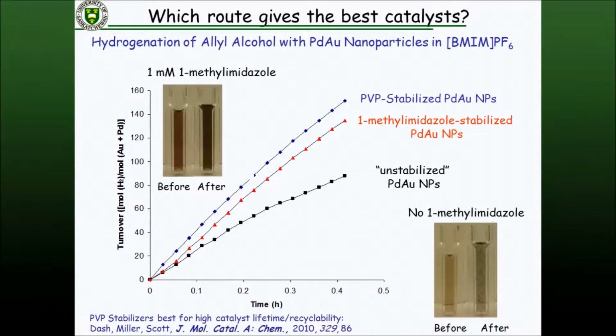And this came out true as well for catalysts. And this is an unstabilized system, actually a palladium-gold bimetallic mixture, so we took palladium salts and gold salt and reduced them together. If we had no further stabilizer beyond the ionic liquid, we see the hydrogenation activity drop off very quickly, and you can actually start to see the precipitate of the particles, the aggregation of the particles in the system. You add the methylimidazole impurities back in, stabilizer impurities, if you will, much better stability. Or if you come in with polymer-stabilized particles to begin with, you get a much more stable catalyst that you can use and reuse for multiple catalytic cycles.